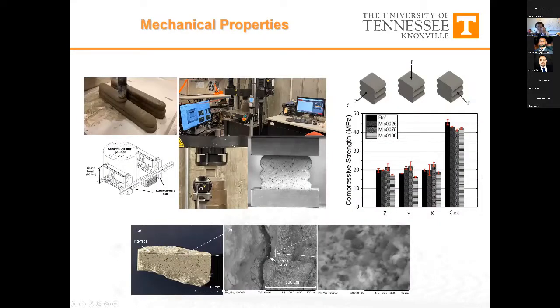We further tested the mechanical property. We are not going to talk too much about the details, but we tested the printed sample in 3 of its orientations, in X, Y and Z, because of the anisotropic behavior of the printed bead. And we compared the mechanical property versus the cast sample.